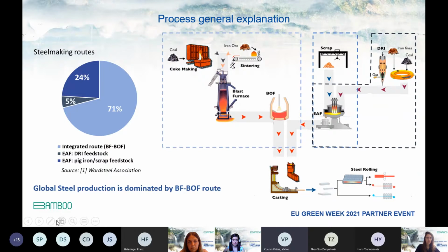So basically, and I will put the pointer, to produce steel from the integrated route, we require carbon that comes from the coal and iron that is in its natural form oxidized in the form of iron ore. So in both sinter process and coke plants, we transform these raw materials into the right elements to be introduced in a huge reactor, the blast furnace, from which we produce liquid iron. And this liquid iron is further reduced in a Linz-Donawitz process, the BOF process, by injecting oxygen. In that case, we generate liquid steel. It's then cast in the form of semi-products, typically slabs, blooms, billets.